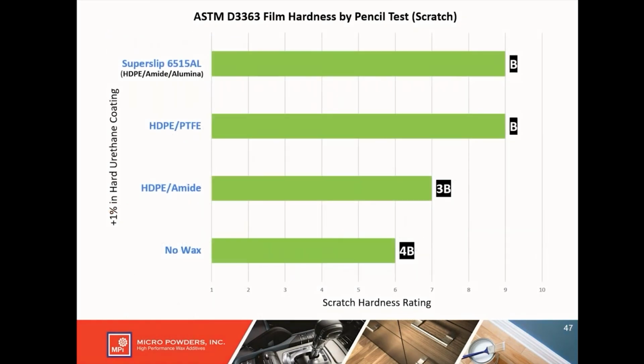Here are those results. So we're looking at pencil scratch hardness again, no wax. This is a hard urethane in this example. No wax, 4B. 1% of high-density polyethylene amide wax improves to a 3B. 1% of high-density polyethylene PTFE, that improves to a B. And we get equal performance, in this case, to the PTFE-based product with SuperSlip 6515 AL, high-density polyethylene amide aluminum oxide, so equal to a PTFE-based additive.